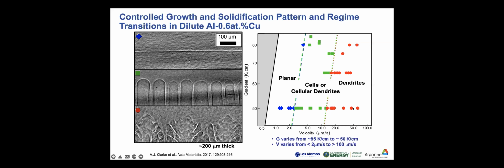Here, all the solid symbols correspond to bottom-up directional solidification. And one thing that was interesting to us right away is we noticed here this black line, solidification theory, would predict the transition from the planar to the cellular growth regime to be at much lower velocities than is actually seen experimentally. So that was something that was fairly interesting to us. To explore this a little bit further, what we did is we did some selected experiments that were top-down directional solidification, and then we can see these growth regime transitions shift to even higher velocities.